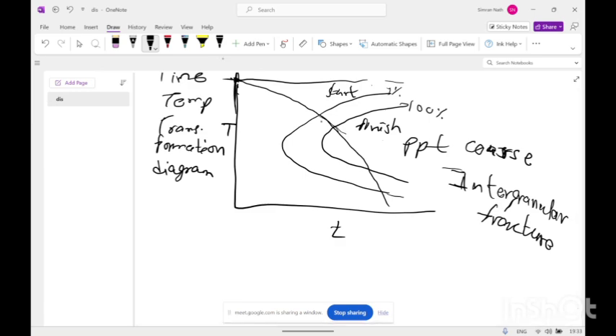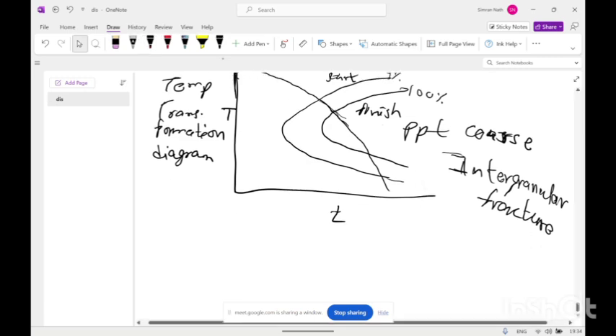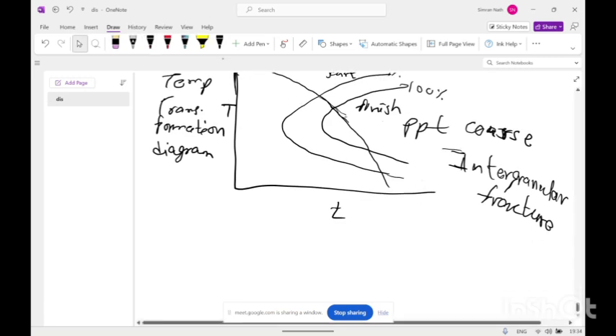Because in the low cooling rate, the heterogeneous nucleation can only happen at the grain boundary, and the homogeneous nucleation is low at the low cooling rate. So the copper is segregated to the grain boundary region, so that will lead to the formation of coarse precipitate around the grain boundaries and intergranular fracture.